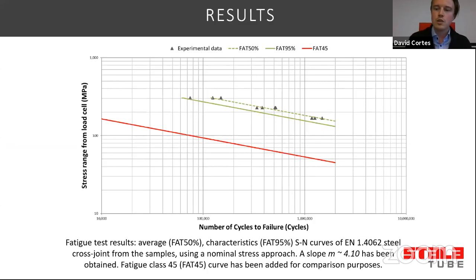We achieved 150 megapascal FAT class with 95% certainty, and 165 megapascals with 50% certainty. And the red curve is the FAT 45 curve, for comparison purposes. So you need to remember here that we haven't ground these welds, we haven't used any hammering nor HFMI, so there's still room for improvement. So we achieved pretty good results with that.